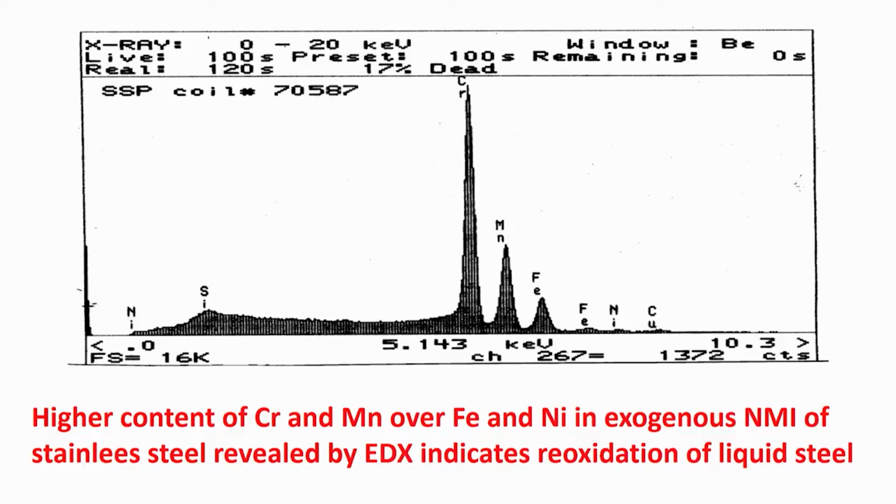So, when we next make the steel, we have to be careful about oxygen ingress. Maybe we have to use a greater amount of argon sealing where the oxygen ingress has taken place. That means possibly we have not used an adequate amount of argon. So, argon sealing was not proper, and some oxygen aspiration, oxygen ingress has taken place. We now know that we have to be careful.